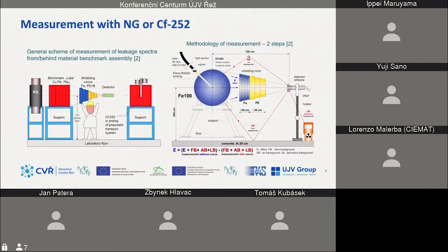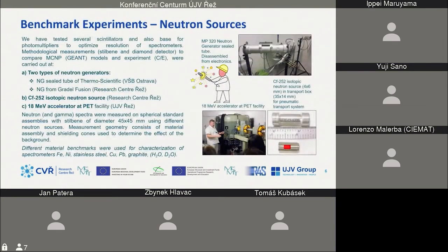How we perform the measurement. So we have two ways. At the beginning, using the neutron source based on isotopic californium, which is quite small, as you see in the preview. This is to scale, so it's around 3 centimeters in length and 1.5 centimeters in diameter. There is a small amount of californium, producing 10^9 neutrons per second.